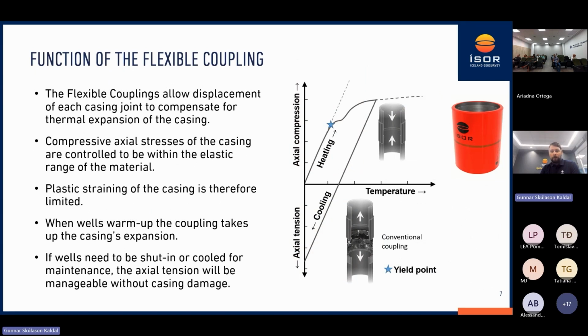So how does it work? They allow displacement. If you look at the graph here on the right-hand side, we might be drilling at cooled conditions. Here we start at the drilling conditions, then the well heats up, and we go past the yield strength and develop permanent strains in the casing, and the well could be running like this for years. If it cools down again, it will not go back the same route. It will develop high stresses in the tensile direction, so we could get failure like this. It depends on how high the temperature reaches and how high these strains are.